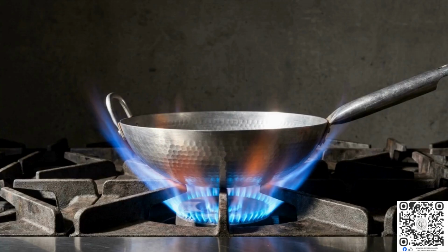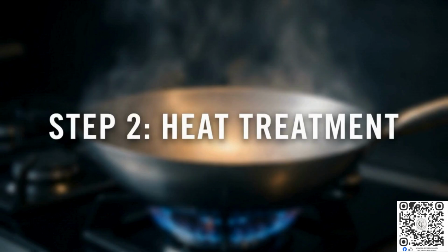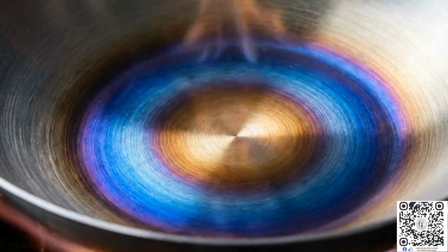Dry the pan completely, then place the wok over your stove's maximum heat. We are going to temper the bare metal in a process known as bluing. Within minutes, the metal reacts. The silver steel turns golden, then shifts into a deep, vibrant blue as it reaches peak temperature.